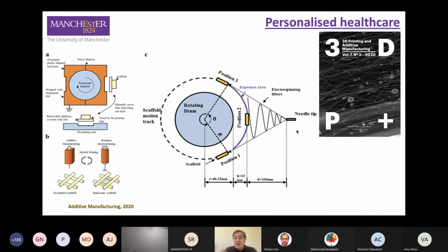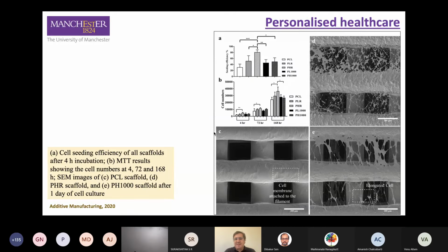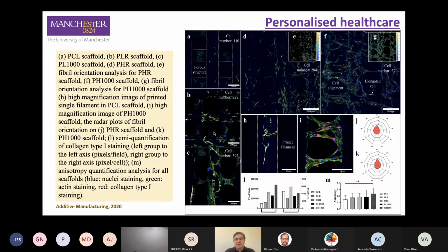We are also combining techniques. In terms of extrusion, it is important to create structures with large pores to allow fluids to flow, to supply oxygen and nutrients to the cells there. But very large pores create a problem in terms of cell growth. So we decided to combine electrospinning and extrusion, and again, we published a paper last year about this. We use a rotating drum, and by adjusting the electrospinning properties, it was possible to create a dual construct with very aligned nanoscale fibers, promoting cell growth and also controlling the orientation of cells in our structures.